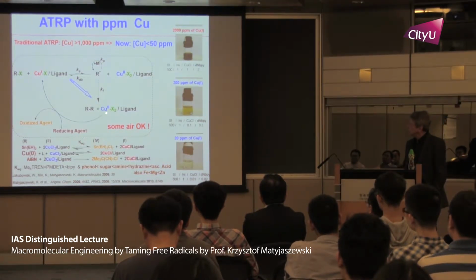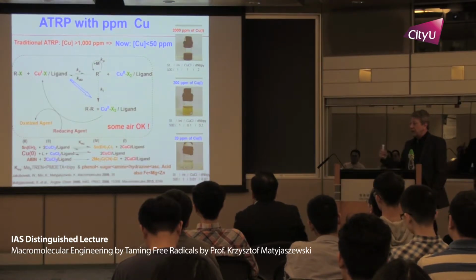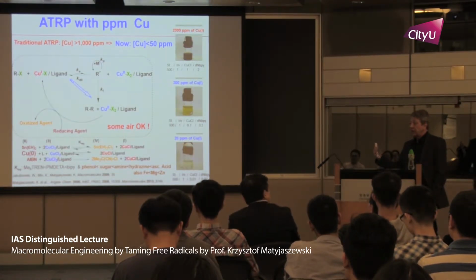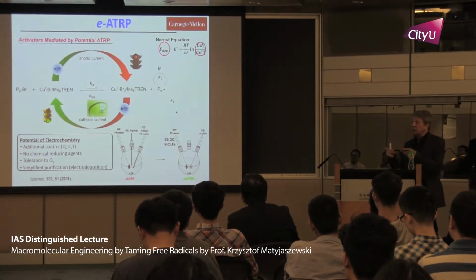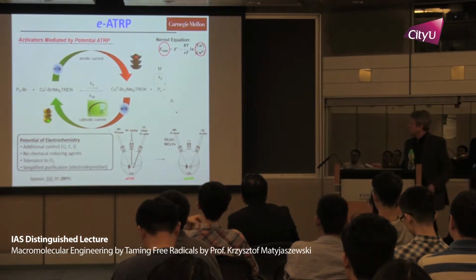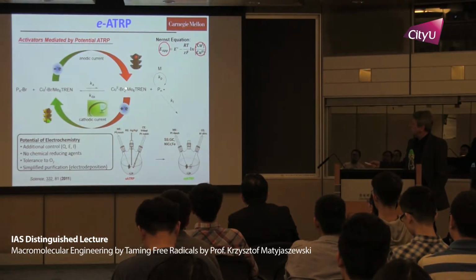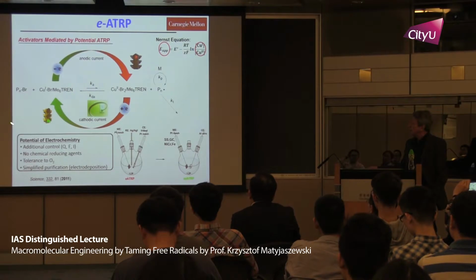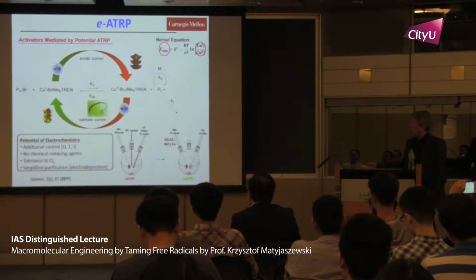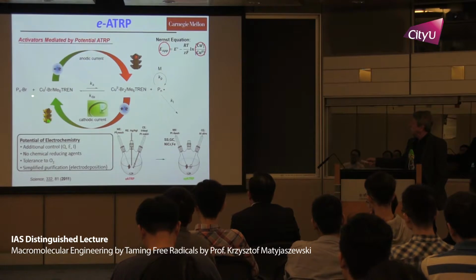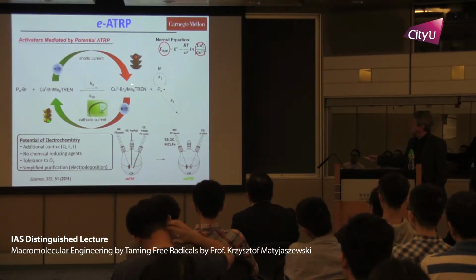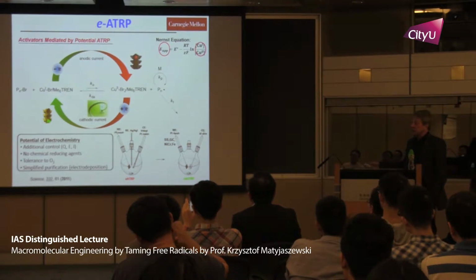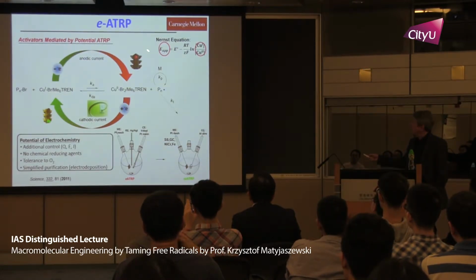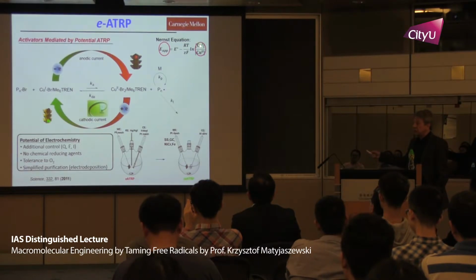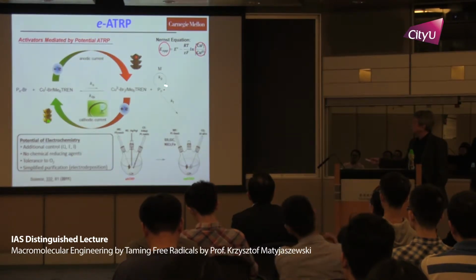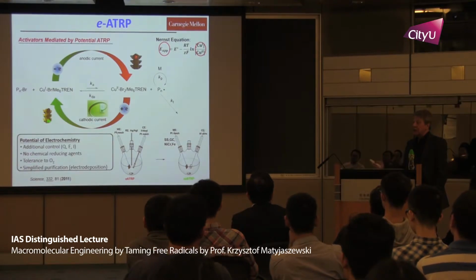I mentioned to you, this is an electron transfer reaction. So can I inject electrons, not by chemical means, but for example, by plugging a battery into the system? In that case, if I apply cathodic current, I reduce copper 2 to copper 1, and I start the reaction. But if I switch current, I go to anodic conditions, I oxidize copper 1 to copper 2 and stop the reaction. And according to the Nernst equation, the applied potential should define the ratio of copper 1 to copper 2, which means concentration of radicals, which means rate of the reaction.